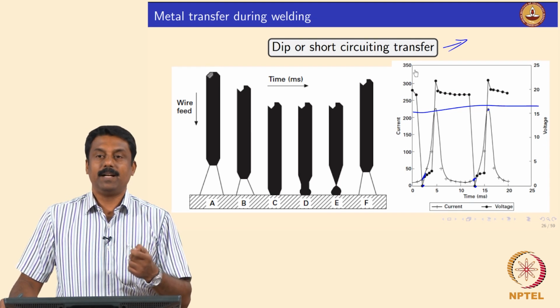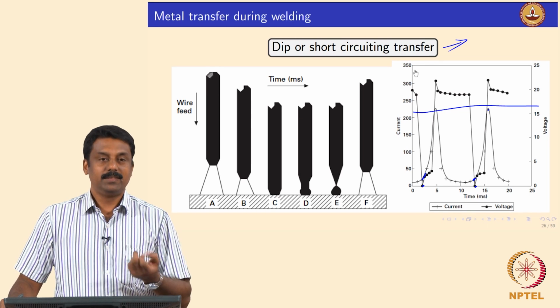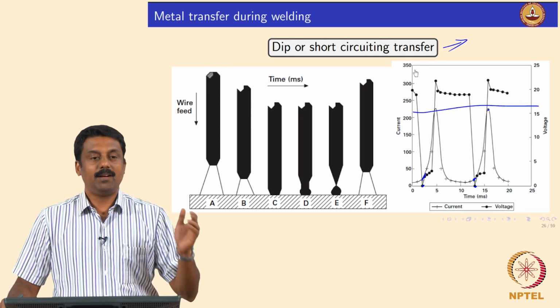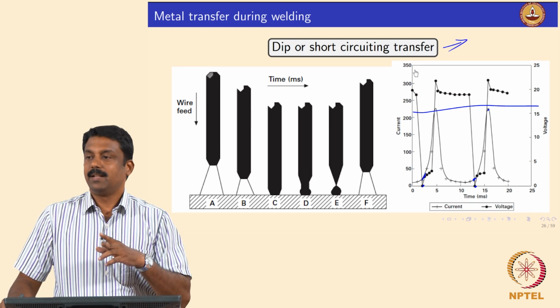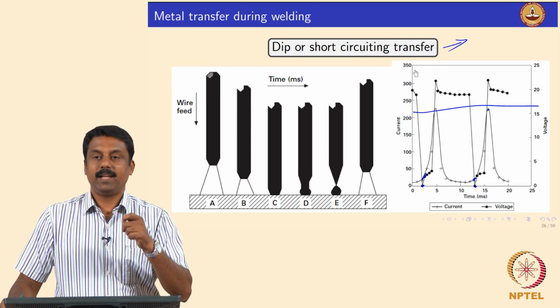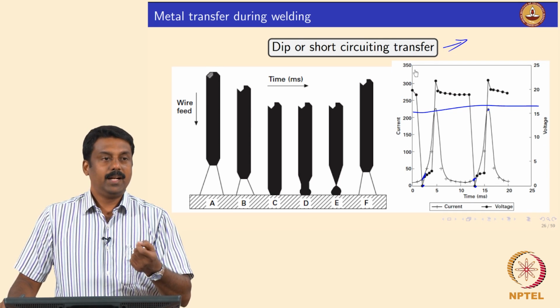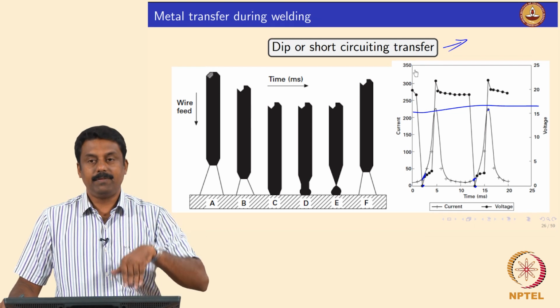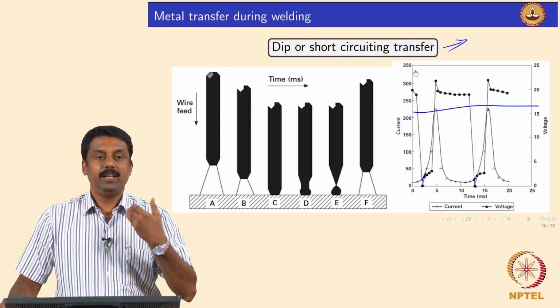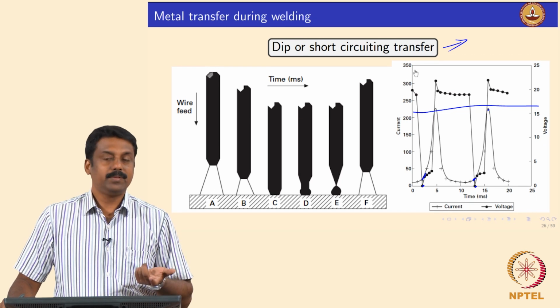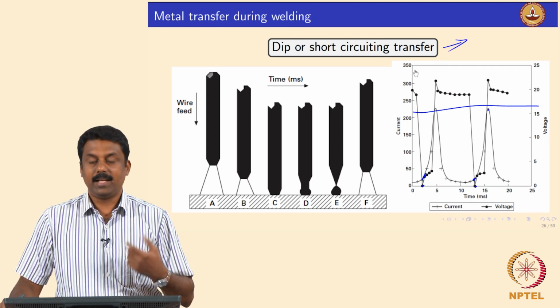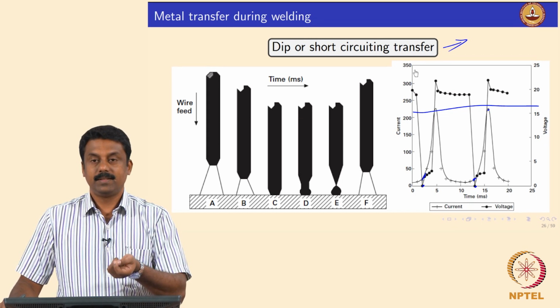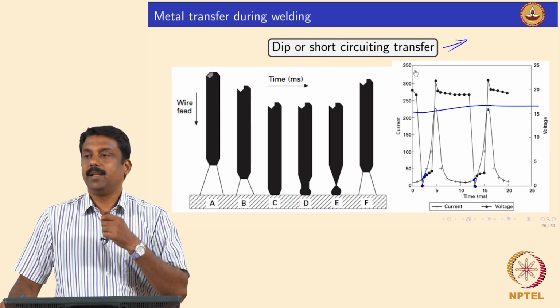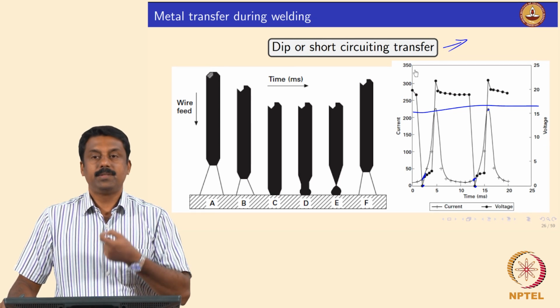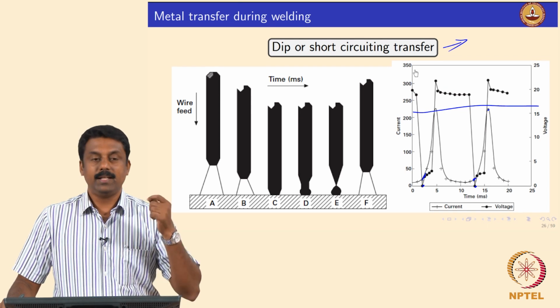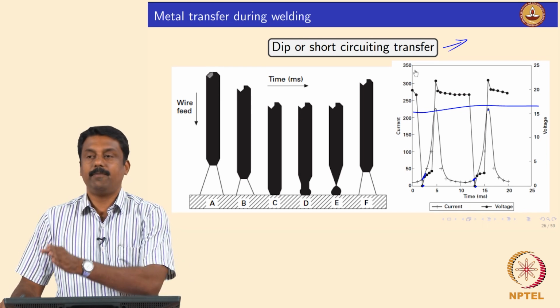So, that is why we use synergy in advanced power sources. It is all synergistically controlled, because for a given composition and filler diameter, the program is already there. So, what will be the feed rate? What current does it have to use for a given pulsing, and how much is it going to melt? And if it is melting, how much feed rate does it have to maintain, so that it can establish short circuiting for a given time interval.